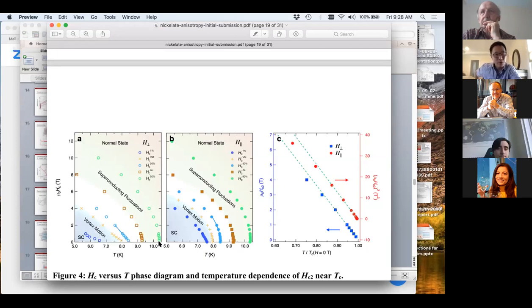One of the motivations, from an applications point of view, of infinite layer cuprates was the hope, from a technology point of view, of having an isotropic upper critical field. And it never really quite worked. I think the anisotropy was still a factor of 5 or more. Namely, it was something like half a nanometer, 0.4 or 0.5 nanometers out of plane and a few in plane. So that was the cuprate case. Yeah, so quite different. Okay, thank you.